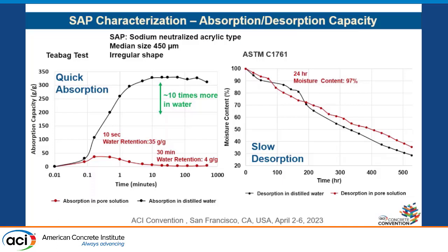We measured the absorption and desorption capacity of SAP using the teabag test and also as per ASTM C1761, which is used for lightweight aggregate. And we realized that there's a huge difference in the absorption capacity when we are testing our SAP in water or testing our SAP in a mixture associated with the 3D printable concrete. It's like 10 times the absorption rate decreases.